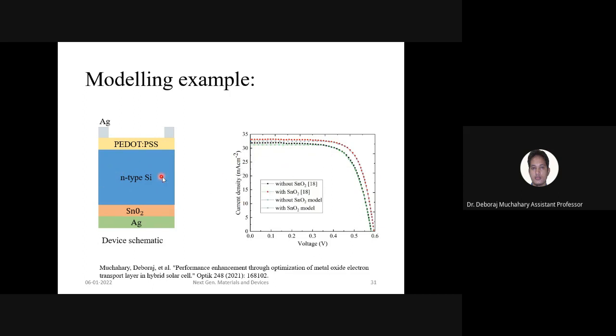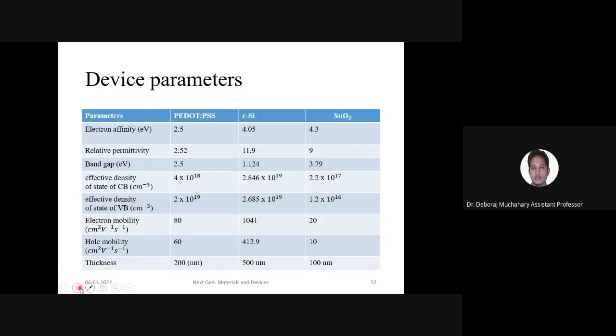After that, we have studied the effect of the interface defect density and the effect of temperature on these IV characteristics. So these things we have done. These are the parameters we have inserted into the simulator, like electron affinity, permittivity, band gap, density of states, hole mobility, electron mobility.